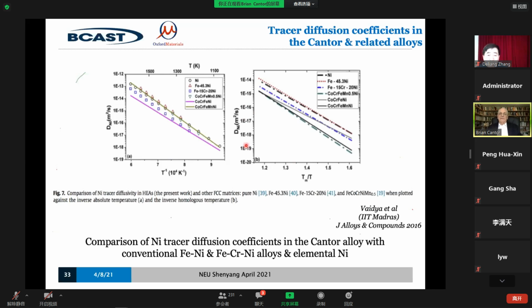And we're plotting the diffusion coefficient against the normalized temperature, normalized to the melting point. And you can see that the Cantor alloys are slower by between half an order of magnitude and an order of magnitude than the other FCC materials of similar kind of components, but not multi-component. So there is a slowing down effect.